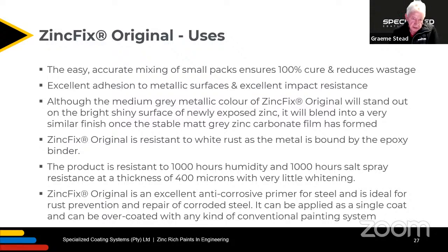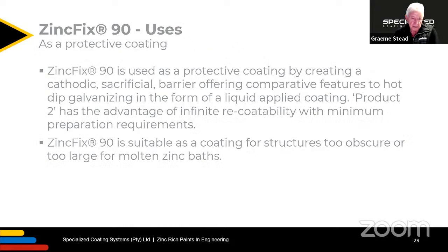And the product is resistant to 1,000 hours humidity and 1,000 hours salt spray resistance. And I once did an SABS evaluation of ZincFix against galvanized panels. And let me tell you, after 1,000 hours salt spray, the galvanizing was not in good condition and the ZincFix was still in pristine condition, but that was 400 microns thick.